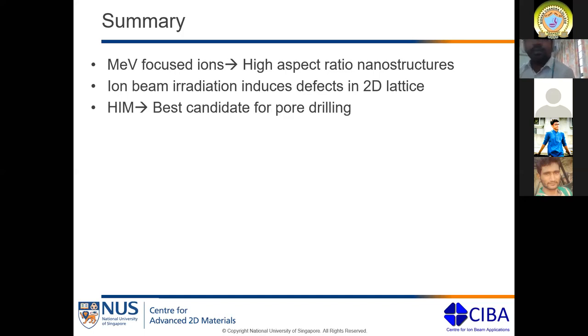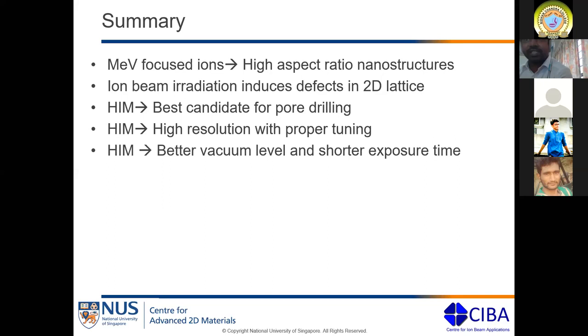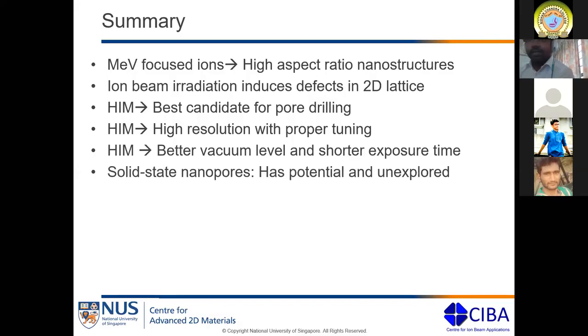In that sense, helium ion microscopy can be a good candidate for pore drilling. It is a direct drilling technique. You can play with the parameters of the helium ion microscope, and you can create different sizes of pores. It is fast, and the vacuum level is very good, so you don't create too much contamination on the surface of the material. And the solid-state nanopores, as I told, are not explored to their greatest extent, and there are many opportunities which are still lying with this kind of technology.